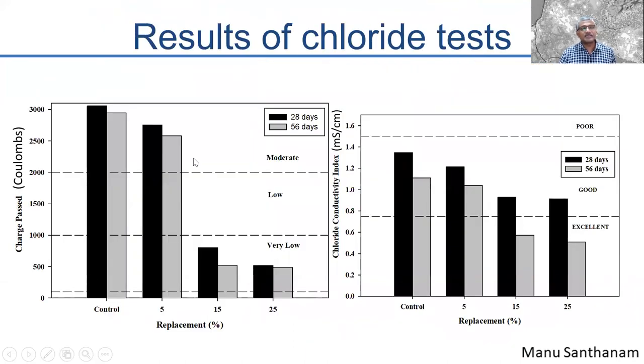So what you see here are the results of the charge passed in coulombs with the replacement level. When I replace up to 5%, I marginally reduce the charge passed. So I'm not really making a major difference to the durability, but still I'm cutting down cement usage. That's obviously a major impact. When we go to 15 or 25%, we have brought down the chloride charge passed to a very low level. And this is a performance which you expect again with very good quality fly ash.